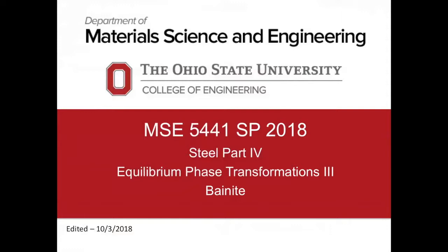If you just do some EBSD or optical microscopy or some SEM backscatter and secondary imaging, it's very difficult sometimes to tell bainite from ferrite, and sometimes it's very difficult to tell bainite from martensite, right?